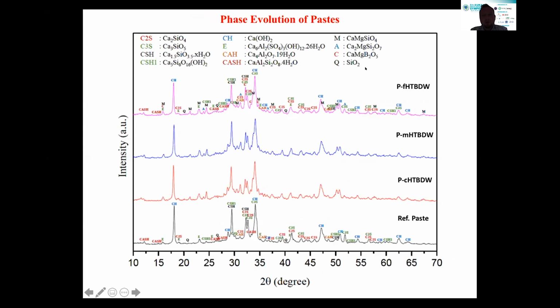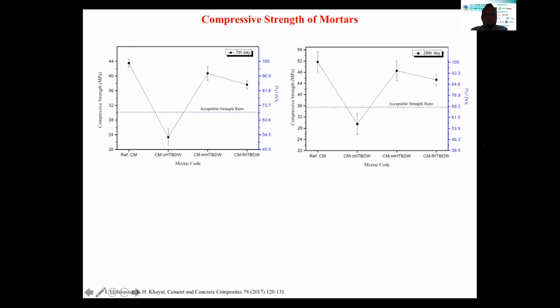After the heat treatment of the waste, some calcium magnesium based phases and also quartz are formed in the structure, and we observe these phases as minor crystalline phases. But in all XRD patterns, the same hydration products were detected.